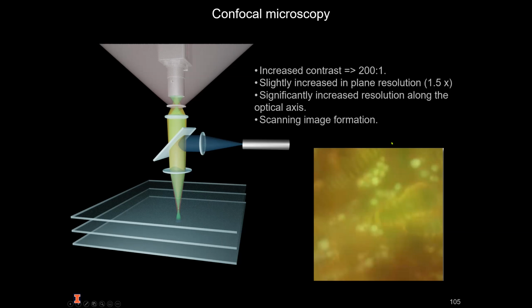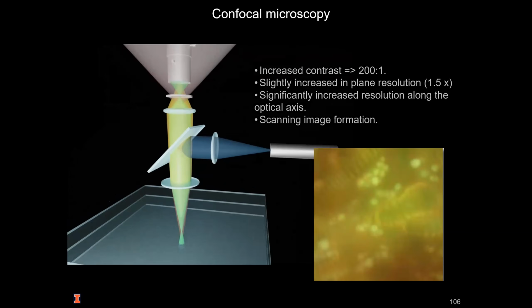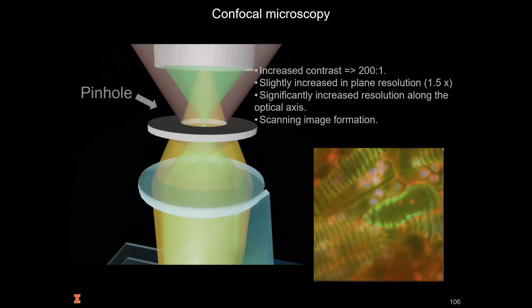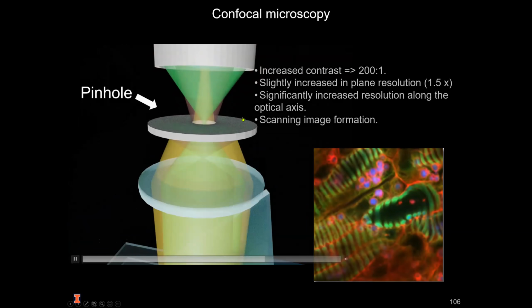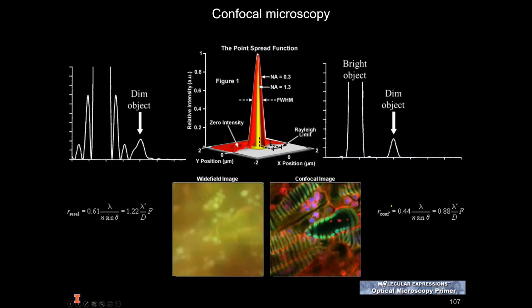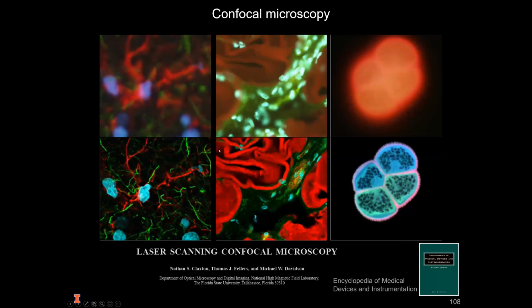The function of the pinhole is to block most of the light coming from the out-of-focus regions of the sample. The more we close the pinhole, the more out-of-focus light we block, and this increases the contrast ratio between the focused and unfocused light, making the images much sharper. Besides this increase in contrast ratio, the confocal microscope also has a slightly increased lateral resolution, so the improvement in quality is quite noticeable.